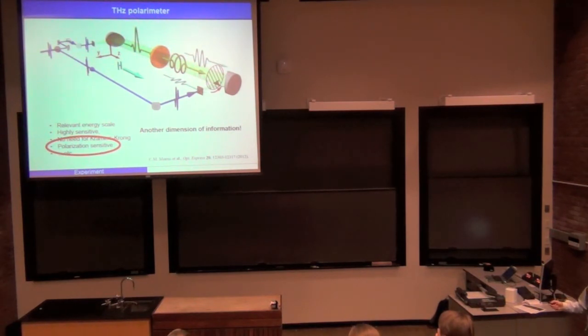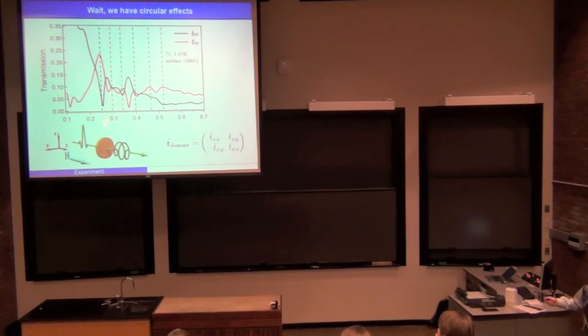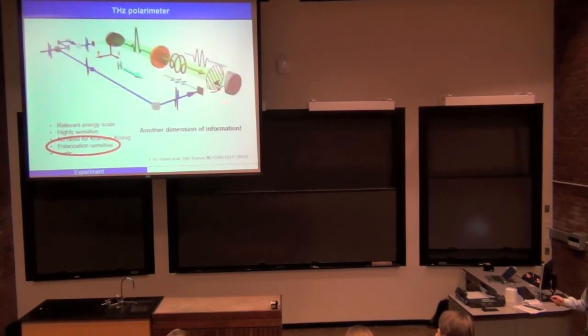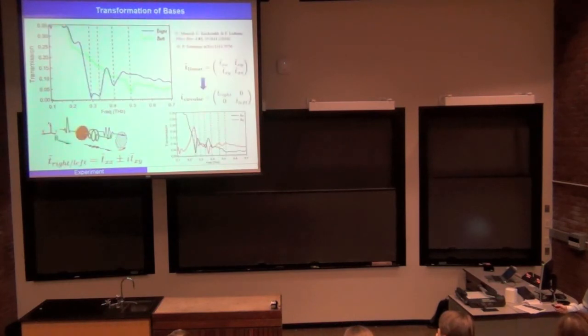well, another thing I should say is these two spectrums, the parallel and perpendicular polarization, are measured at the same time simultaneously. We developed an interesting technique at Johns Hopkins called Polarization Modulation polarimeter. And here we spin a polarizer and feed the signal into a lock-in at twice the spinning frequency of this polarizer. As a result, we are able to measure the two perpendicular channels of the transmission at the same time. This gives us another dimension of information, which would be useful.